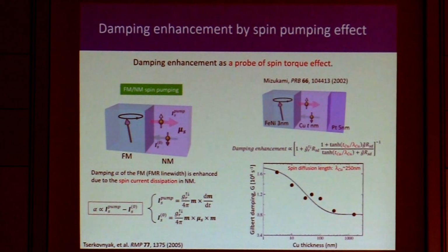The typical experiment was done by Mizukami and co-workers a long time ago, using copper as an adjacent material. They saw the Gilbert damping decrease as the copper thickness increased. By using this equation, they were able to characterize the spin diffusion length of the copper to be 250 nanometers.